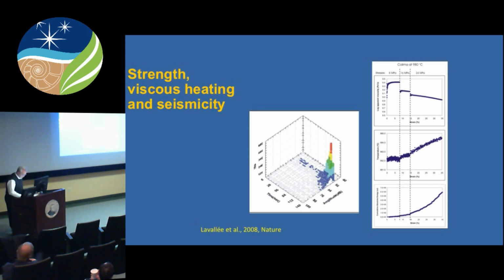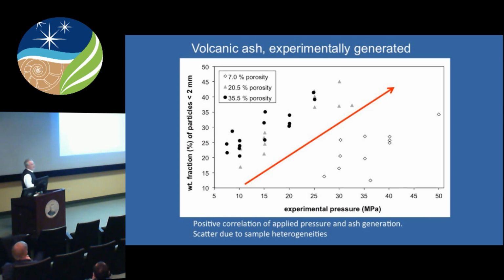Okay? And here you see the number of acoustic emissions. In other words, small fractures in the material before it disintegrates and stops the experiment. And you see it runs off in a nonlinear way to higher values. And my colleague Yan Lavallée and my colleague Michael Heap are convinced that they can use this to predict volcanic fragmentation events. Of course, at the end we get all the ash. It means we can actually do petrology on the ash, and we can do fractography on the surfaces of the ash. And Tobias Thürig from Würzburg has just done some of this.